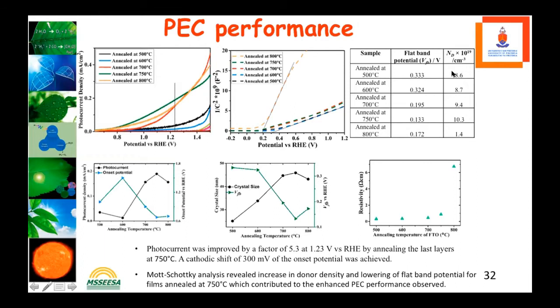So we have compared the flat band potential, and we took the samples, the flat band potential and the carrier density. And we found that the 750 was giving us better results, which will be very valuable for us. So what is it that we are looking for? We want a very good photocurrent, where a cathodic shift of 300 millivolts of the onset potential was achieved due to annealing at 750 degrees Celsius.